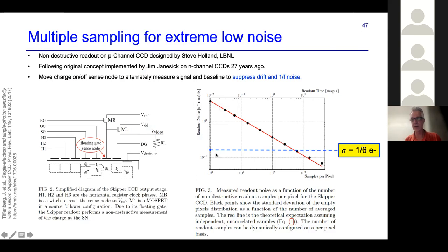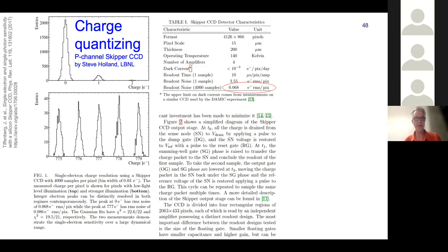And so in the blue dotted line, we've got the magic 6 sigma threshold, where sigma is a sixth of an electron. And here is an actual measured histogram of an image. And it shows that each electron level, whether you have 0, 1, 2, or 775, 776, can be discriminated in post-processing. And so when you threshold the data like this, you've turned the 0.15 electron read noise into 0 read noise, but you haven't suffered any coincidence losses. You're not required to read out at a high frame rate. Your CCD can have a well capacity of 350,000 electrons.